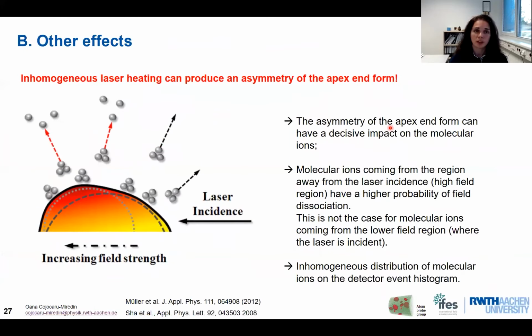So there are also some other effects. For example, we know that the laser is hitting the atom probe tip on the side. That means that we potentially have an inhomogeneous laser hitting the apex of the tip. If the laser is coming from this side, we have a higher heat induced inside our sample here. That means we'll have a lower field on this side, although on the other side we will have a higher field. So we have an inhomogeneous field distribution on the apex of the tip.